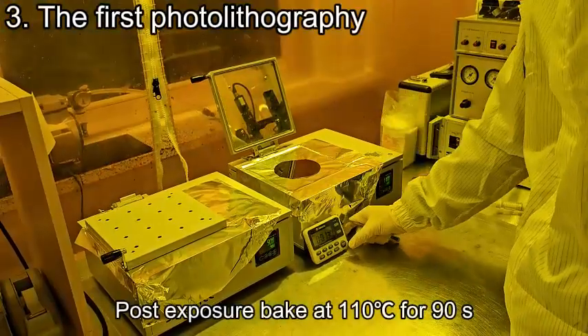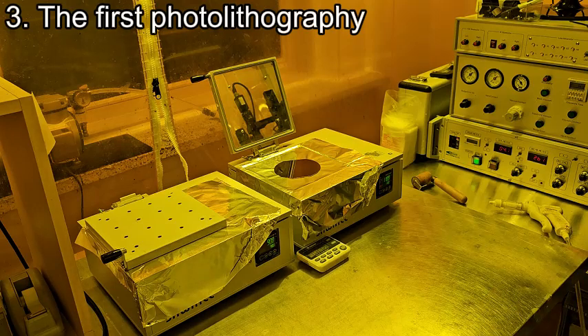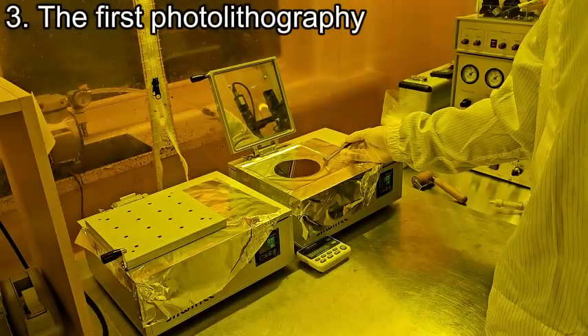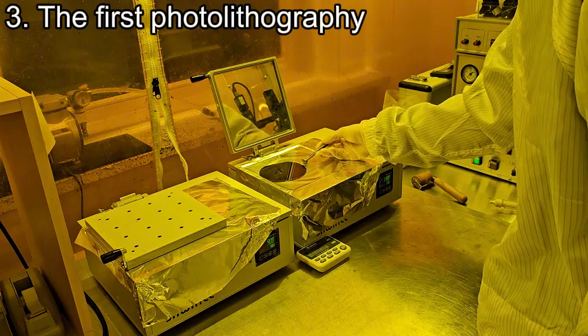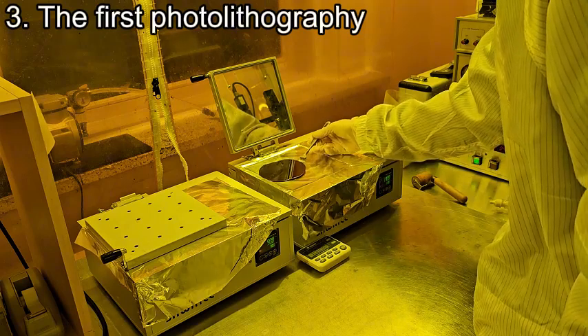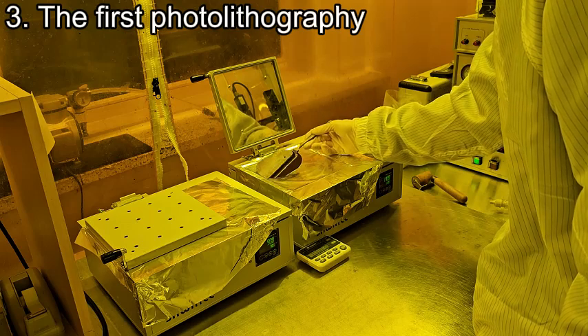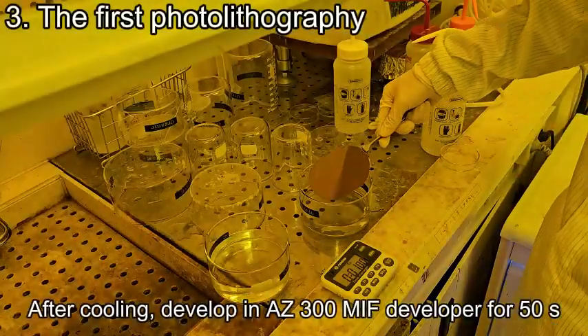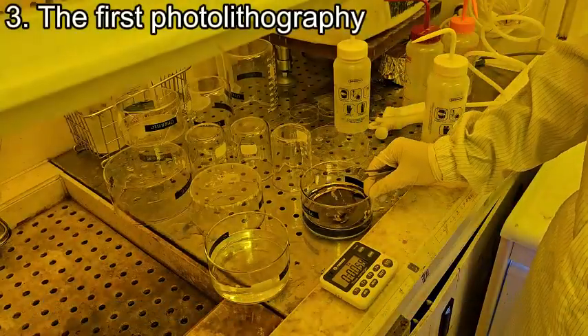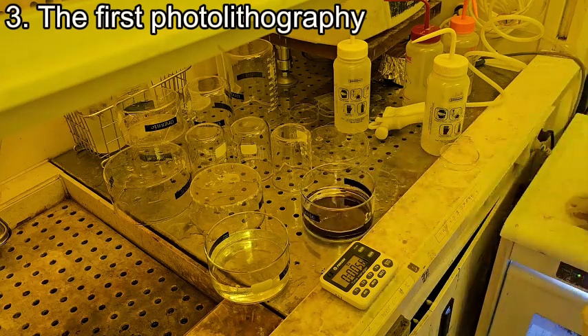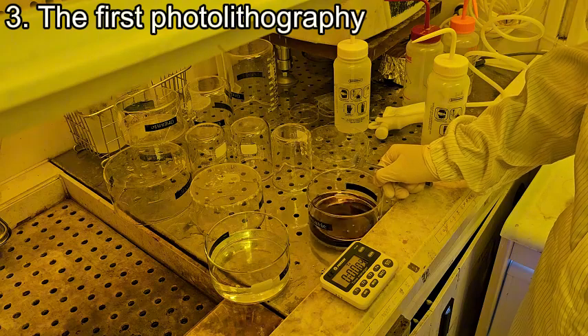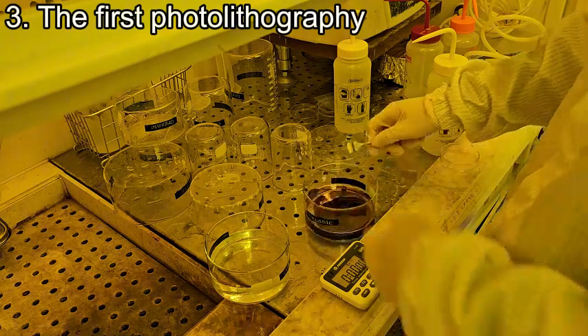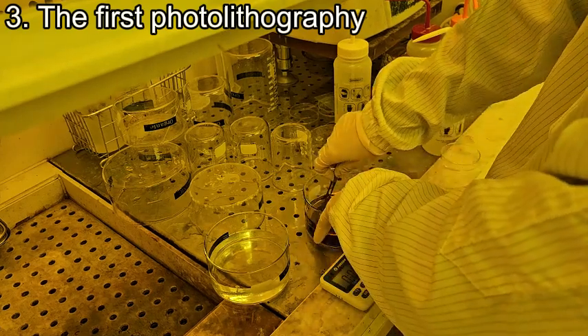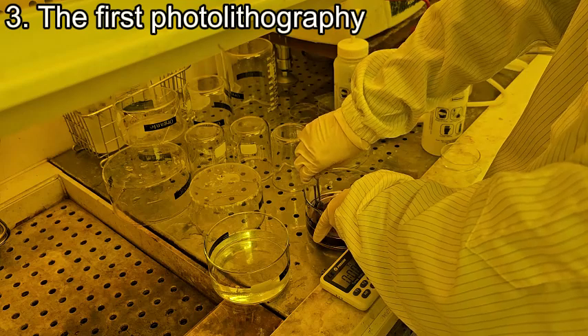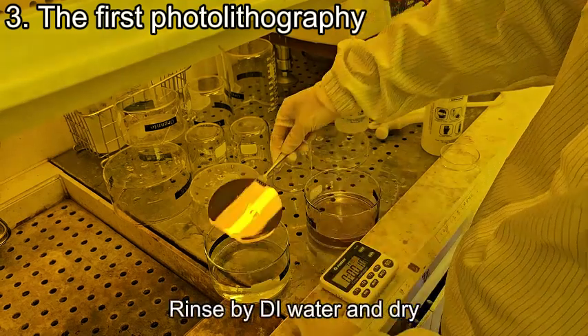Post-exposure bake at 110 degrees centigrade for 90 s. After cooling, develop in AZ300 developer for 50 s. Rinse with deionized water and dry.